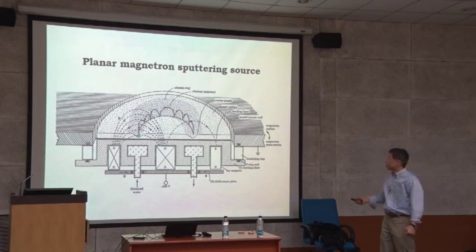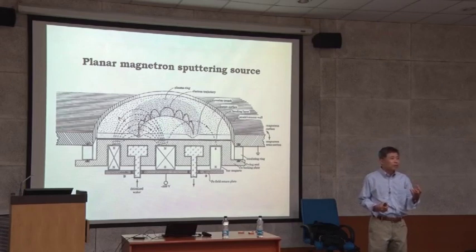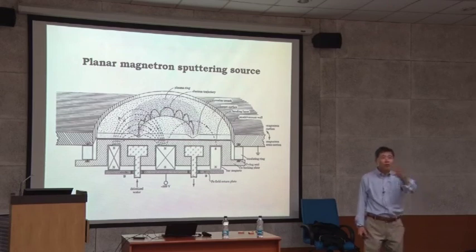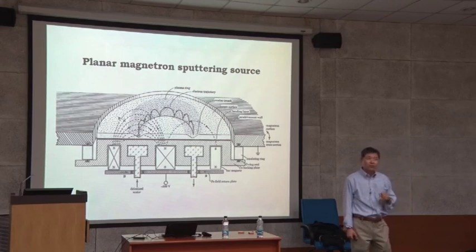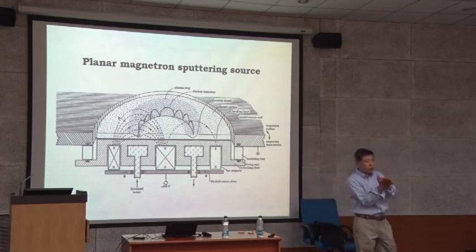Okay, so when you do this sputter target in ceramic, you guys use a sputtering target. How do you mount your sputtering target? Ceramic target, anybody? Do you just mount it directly on the heater block or the sputter gun? There is a backing plate also. Good. Do you use a backing plate or a backing cup? We use a backing plate. Backing plate, okay. So my recommendation to all of you who do sputtering: use a cup. Don't use a backing plate. The backing plate is not good enough to hold this.